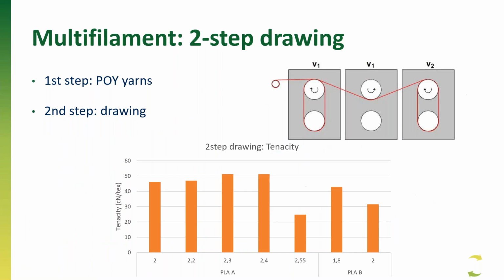And then in the second step, we use these POY yarns and we stretch them again in ovens. We heat them up again, ovens or rolls, both of them have been tried, to really have the solid state drawing as well. So we are using both types of drawing, and you can see here in the image the strength that we create. The tenacity, in centinewton per tex, we create up to 50 centinewton per tex. With the standard FDY process, we only have around 35, sometimes up to 40 centinewton per tex.